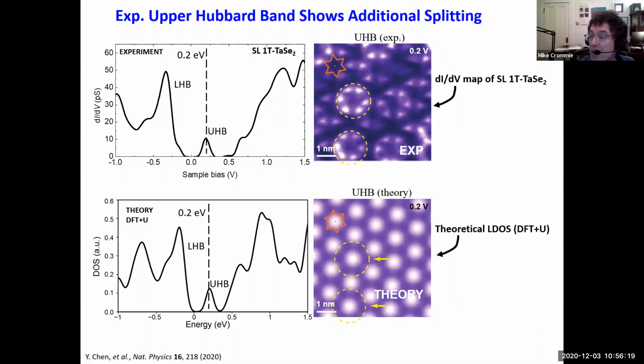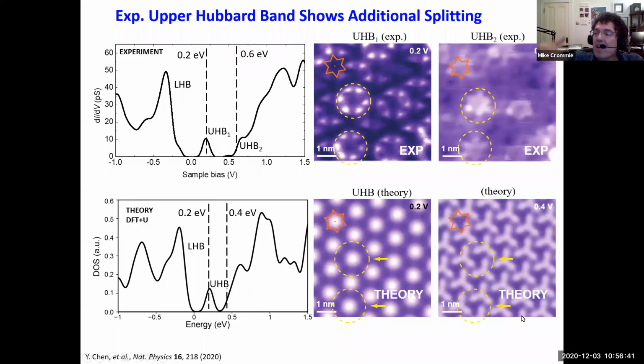Now the theory and the experiment do not match. And that's not a surprise, because this is a Mott insulator after all. It has strong correlations, and the correlation effects are messing up the match. Basically what you see is that in the experiment, we have a depletion of local density of states in the center, whereas in the theory, you have a lot of local density of states in the center. And now if we look at slightly higher energy, once again, the theory and experiment don't match. In the theory, we have a depletion of local density of states in the center, but in the experiment, we have lots of local density of states in the center.